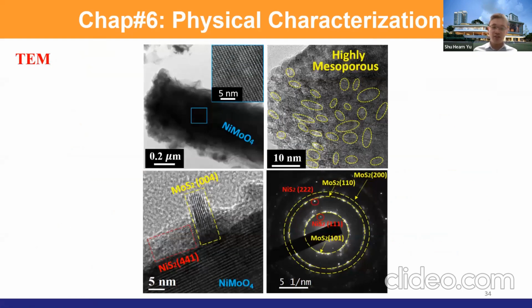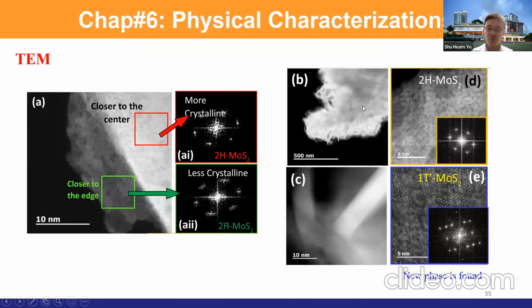All right. So this is a TEM structure. You can see the nickel molybdenum oxide, and the surface is nickel sulfide and molybdenum disulfide. These are very highly porous structures. And we can detect MoS2 and nickel sulfide in the EDX and also the HRTEM. This highly porous structure is very advantageous for the HER reaction because there is extra room and more active sites for the HER.